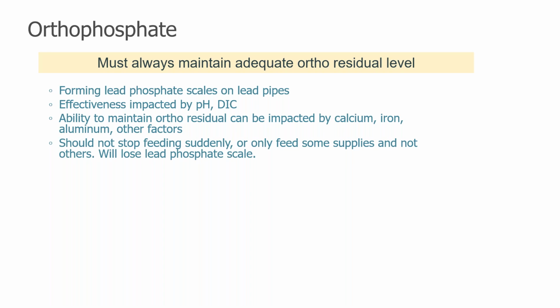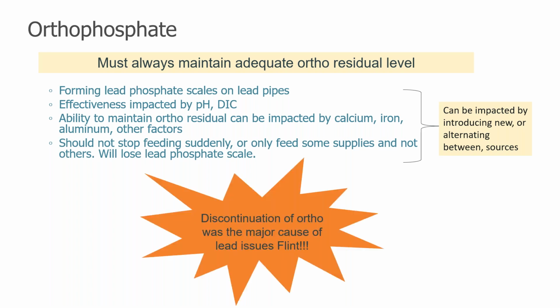Should you stop feeding suddenly or introduce a new supply that has very different characteristics, you can imagine that you are impacting the performance of your orthophosphate. And this is really one of the major issues that happened in Flint. It was discontinuation of the orthophosphate and the whole need to try to convert to the carbonate species, which wasn't successfully done, was a major contributor to the lead release issue. So we've been learning a lot about the importance of feeding orthophosphate and maintaining orthophosphate residuals in the distribution system.